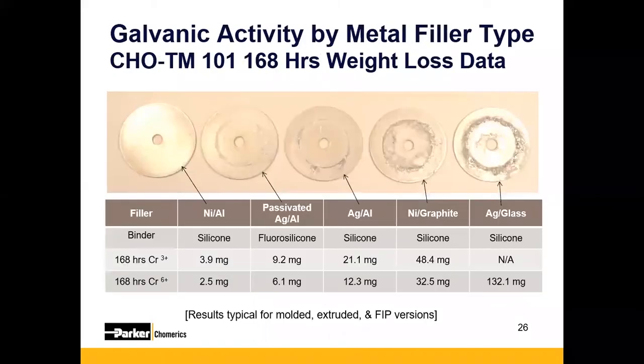So as you can see in this image here, on the left, we see a lot of the corrosion resistant materials, the nickel aluminum, the passivated silver aluminum, and you'll see how much better the coupons look, as well as how much less material, in terms of that aluminum that was dissolved away, as opposed to something like a nickel graphite or a silver glass.